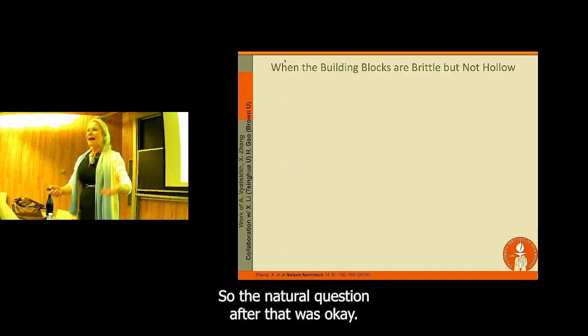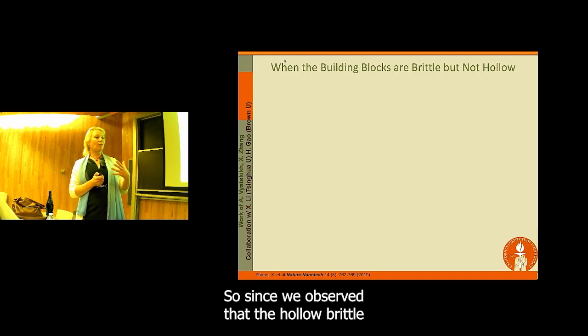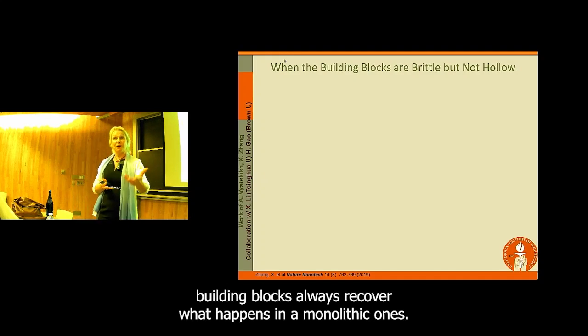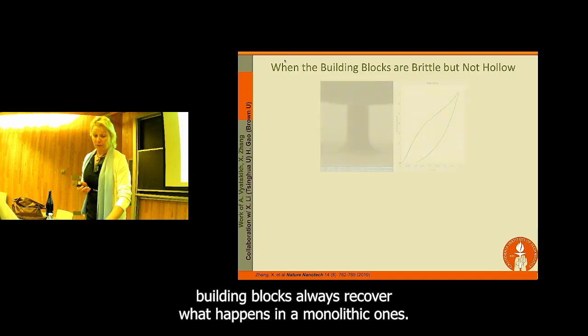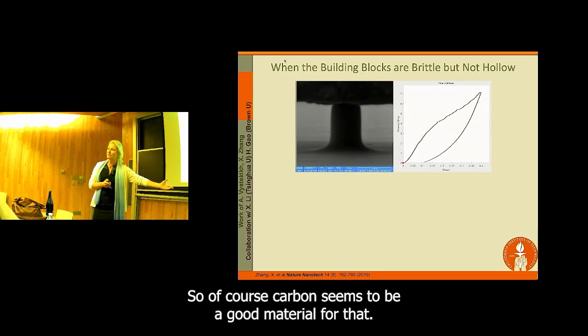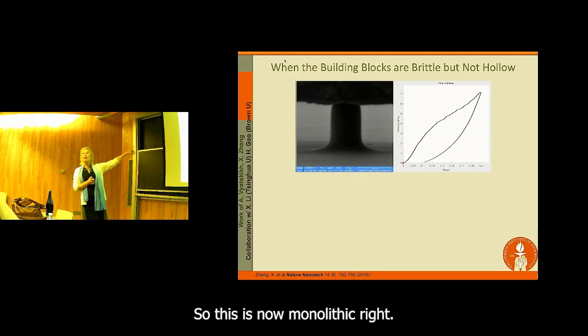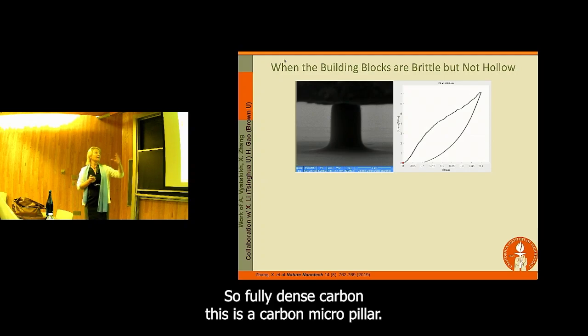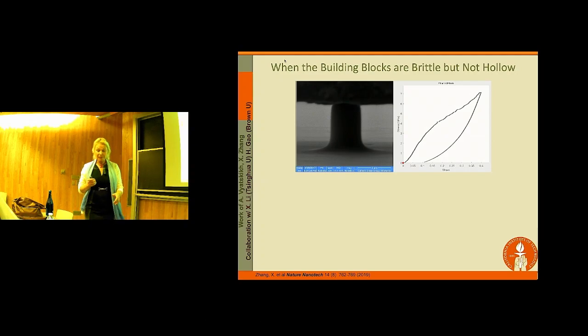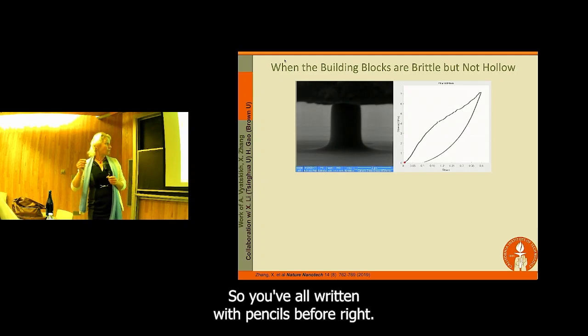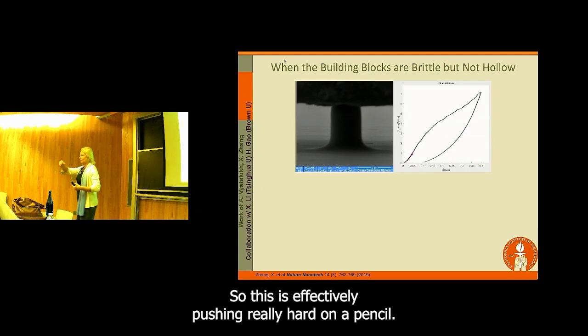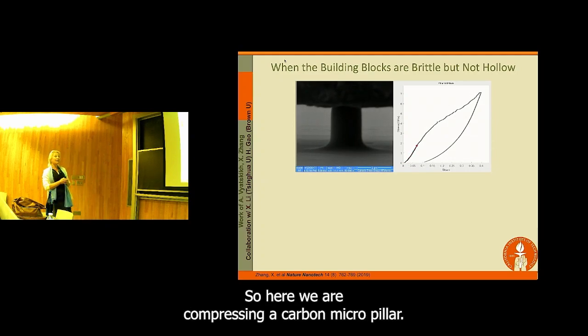The natural question after that was, since we observed that the hollow, brittle building blocks always recover, what happens in the monolithic ones? Carbon seems to be a good material for that. So this is now monolithic, fully dense carbon. This is a carbon micropillar, and we're going to compress it. You've all written with pencils before, right? So this is effectively pushing really hard on a pencil. Here we are, compressing a carbon micropillar.